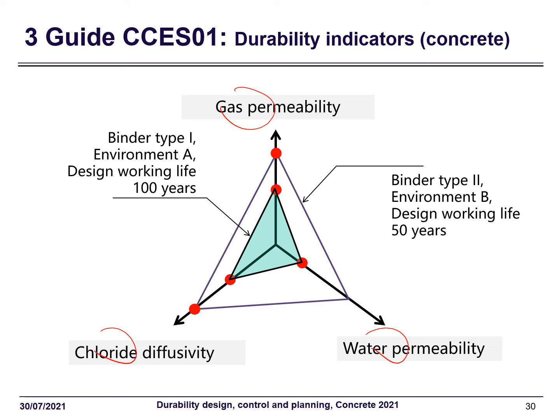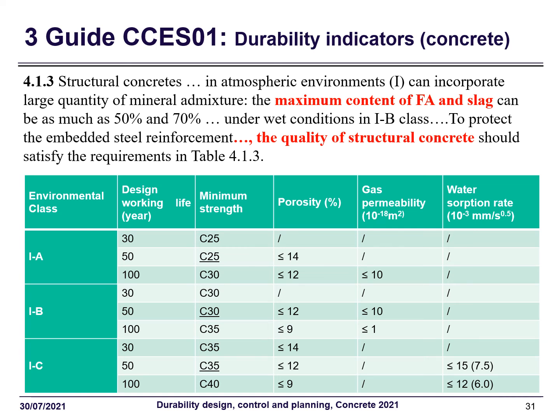So we think that whatever durability model you use after design, more or less you can transfer your requirement into these three parameters. Following this line, for example, we formulate the requirements for structural concrete in atmospheric environments. Here, you can see that on the table, we use the parameters of porosity, gas permeability, and water sorption rate, plus the minimum strength. Those are the property requirements. Of course, in parallel, you will see that we also have requirements on the composition, like maximum content of fly ash and slags. So it's a mixed approach between the deemed-to-satisfy prescription and the performance-based requirements.